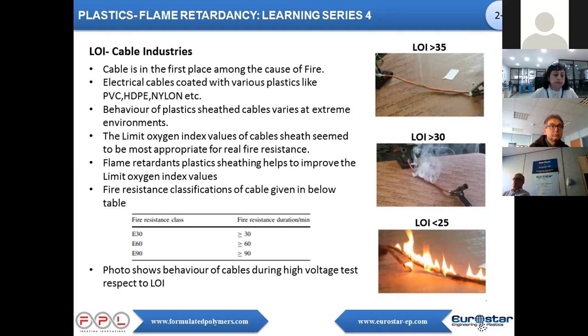In the right side photo, we see in the top photo, cables made of PVC with the highest limiting oxygen index values, greater than 35. It shows low fire and smoke generation, almost nil smoke generation observed. In the middle, the cable is made of nylon, of medium LOI values greater than 30. Fire and smoke generation are little and slightly visible. And the bottom one is a cable made from plain HDPE of LOI less than 25. It exhibits fire, generates more smoke, and almost starts burning. This experiment shows the importance of LOI values in the cable industries.